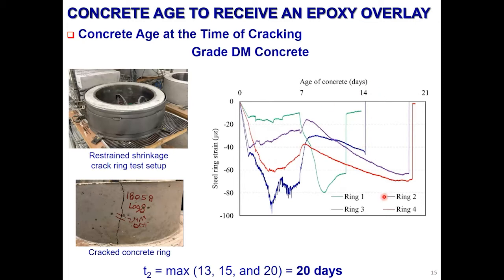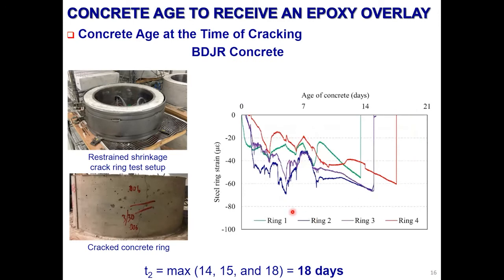So we need to evaluate the cracking age. This is an evaluation in the lab rather than in the field. In the lab, when we use grade DM, that means the mix with slag, it's going to crack after 20 days. We ran a couple of shrinkage rings, and we can see we had to wait at least 20 days before we apply the overlay. The mix with type 1 cement shrinks more than the mix with slag, which is obvious, so it'll crack after about 18 days.